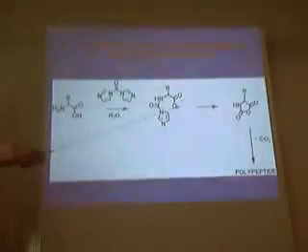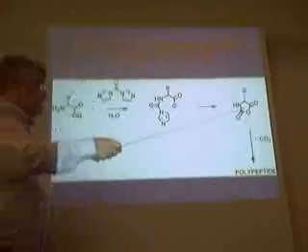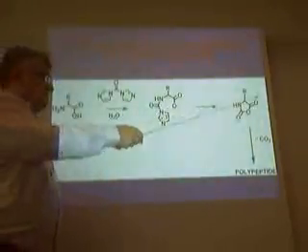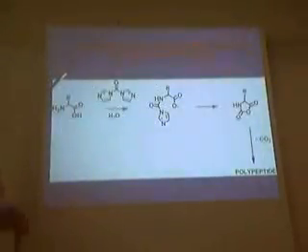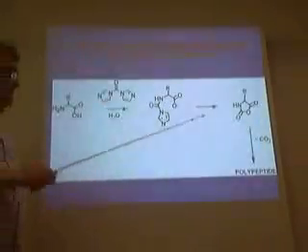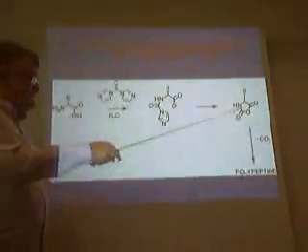In this reaction you take the pure amino acids and react them with carbonyldiimidazole at 0 degrees for 3 minutes, creating this intermediate. We have not been able to isolate the N-carboxyanhydride, but some people, and Orgel, assume that you are forming N-carboxyanhydride as an intermediate. We are now searching for this intermediate by fast NMR methods. Then you polymerize and go to the polypeptide system.